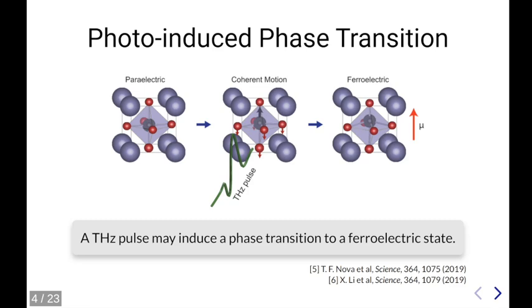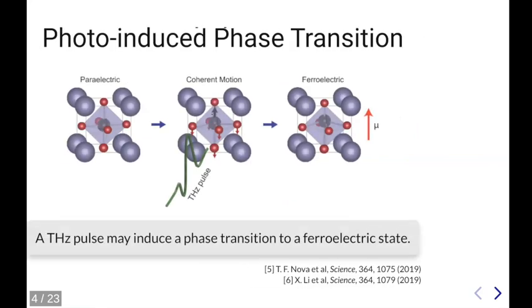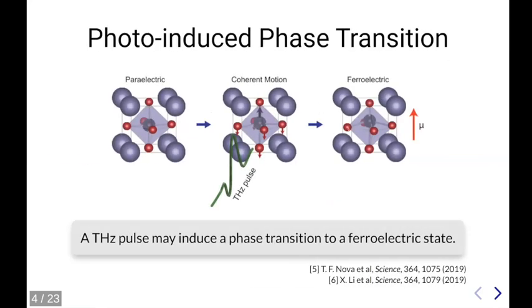So this is something that cannot happen in equilibrium because the ferroelectric state is unstable at equilibrium, but it's happening, apparently, experimentally, only if the system is irradiated with terahertz laser. And indeed, how did the experiment measure this inversion symmetry? It used a probe, second harmonic generation, which generates a signal only if the inversion symmetry is